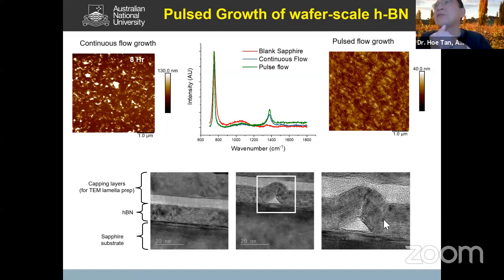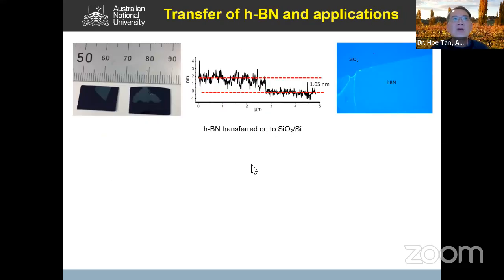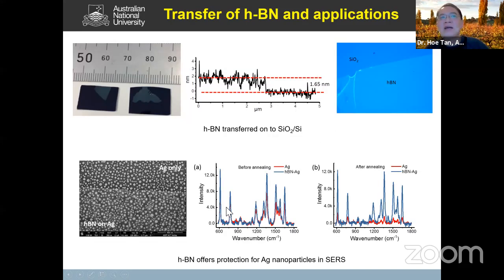And we can actually get rid of this wrinkle. If you can lift off the hexagonal boron nitride, then the wrinkle sort of irons out, okay, without any crack in the film. So as you can see here, we can transfer this centimeter scale hexagonal boron nitride. So we can transfer it on a piece of silicon with SiO2. So you can see that. And we also use this as a passivation layer for our study.